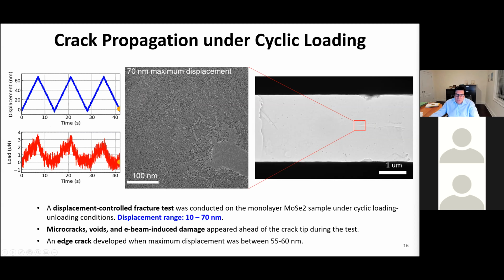So what you see here is the crack tip. This time we don't see the atomic positions because the polymer was thicker in this sample, a little thicker, on the order of 2 nanometers. And you don't see that, but you will see defects happening in the crack tip, like micro cracks, little holes.